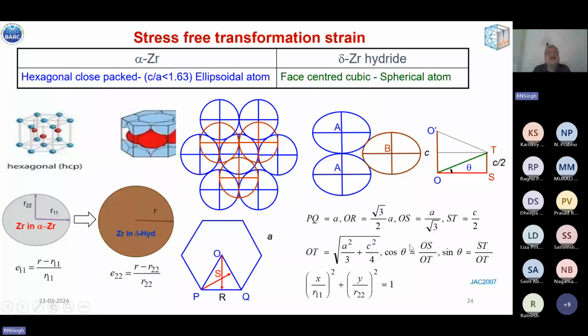So what we did is that we tried to compute this stress-free transformation strain. Here we have alpha zirconium, which has a hexagonal close packed structure, and delta zirconium hydride, which has a face-centered cubic structure. In 1973, in the Journal of Nuclear Materials, one article was published by Carpenter, G.C. Carpenter. What is suggested is that one can determine this stress-free transformation strain by determining the radius of the zirconium atom in the hydride and in the alpha HCP phase.